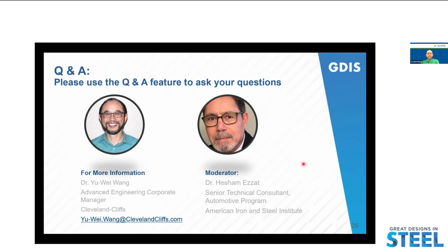The first question is: are the tubes joined together using a continuous laser weld, or is it a laser skip weld? And I think this is referring to the rocker reinforcement. Yeah, it's a good question, Hesham. Yes, they are joined through a laser weld, continuous throughout the length. However, in our test, we evaluated different laser patterns, stitch weld. Our preliminary results show that as long as you have between 50 to 70% of weld, the performance of three-point bending for energy protection does not change significantly.